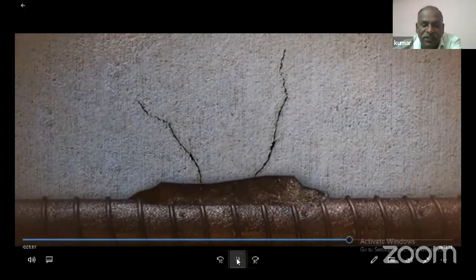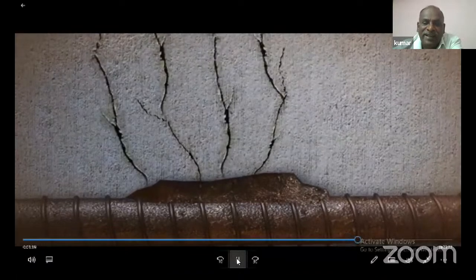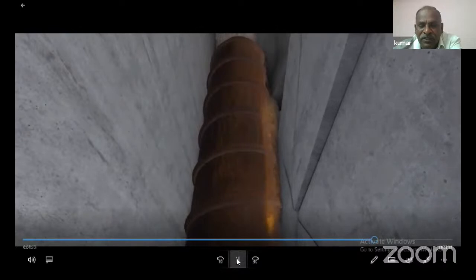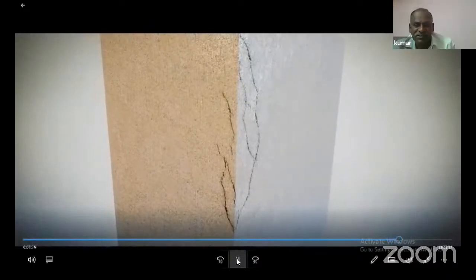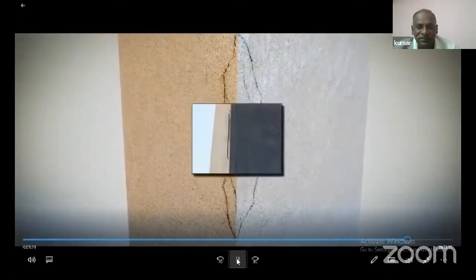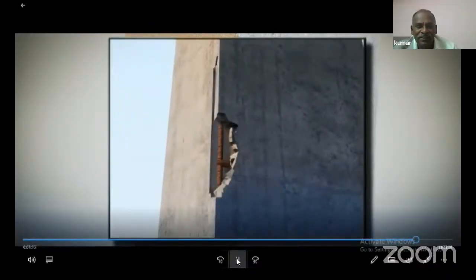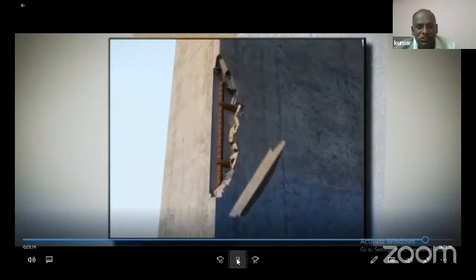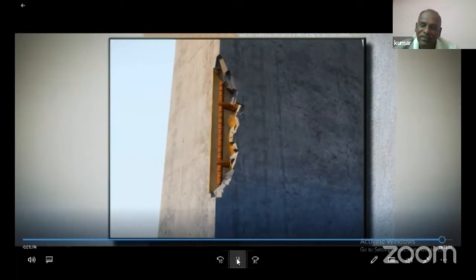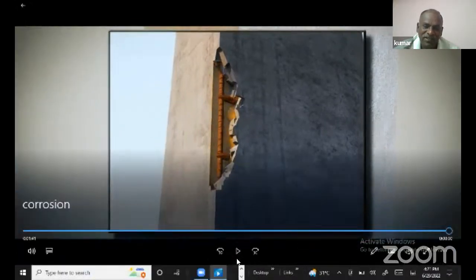See that because of the corrosion product, you will be getting a crack. The corrosion product is of higher volume than the metal loss. So within the matrix of the concrete, pressure is exerted and it is getting spalled. When it is spalling, the steel is readily available for corrosion, and further corrosion and deterioration are taking place.